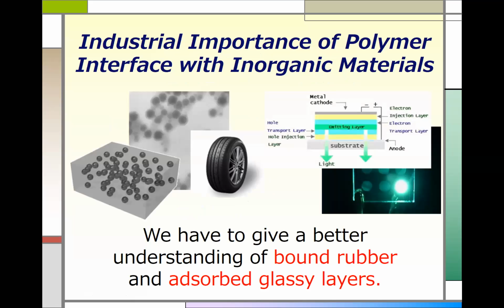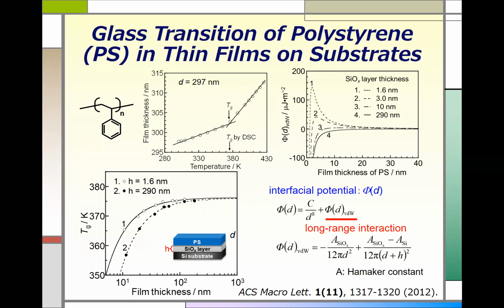So then let me show you how the interface with the solid substrate is important. Take a look at this cartoon showing our sample. This is a thin film of just polystyrene, and I suppose that you're familiar with polystyrene. This is a typical glassy polymer at room temperature. The chemical structure of polystyrene is like this. And the substrate is a silicon wafer with a native oxide layer.